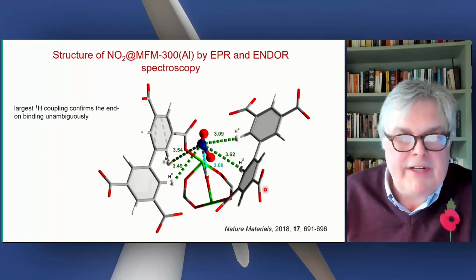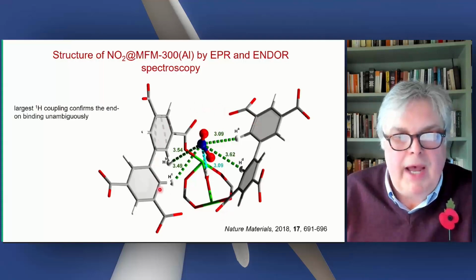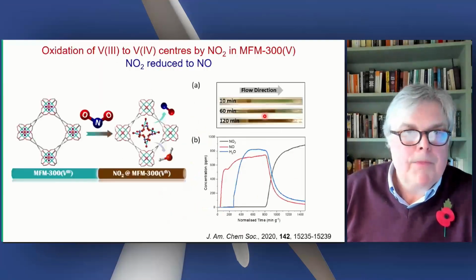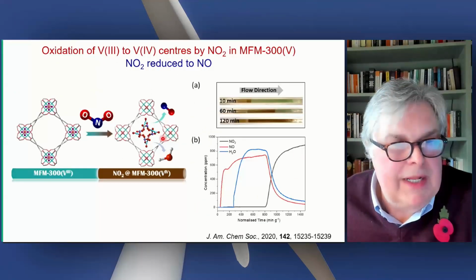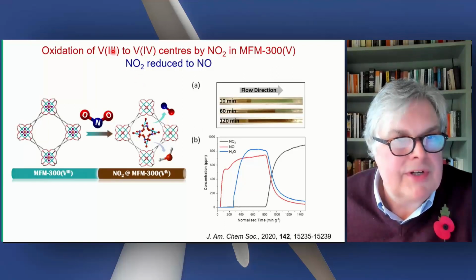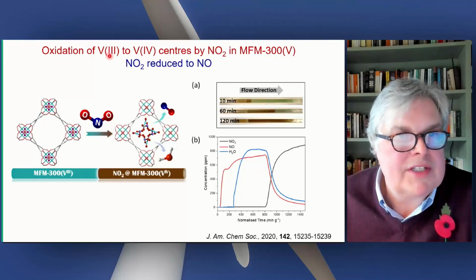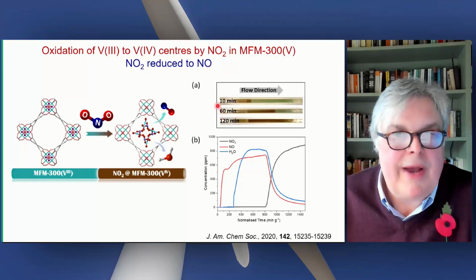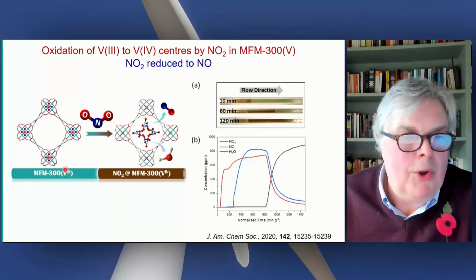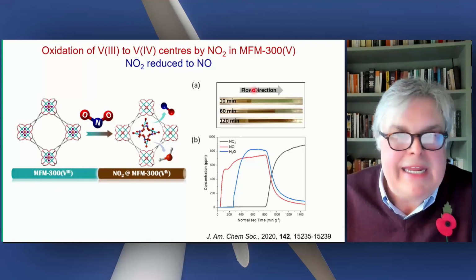This tends to be a very strong motif here in terms of binding different substrates. Now we're going to move to a little bit more reactive chemistry. The vanadium-3, vanadium-4 couple, which I showed you before: you can oxidize vanadium-3 to vanadium-4 using NO2, which is then reduced to NO. So as you flow NO2 through a greeny blue vanadium-3 column, you can see it goes brown because it's oxidizing to vanadium-4.